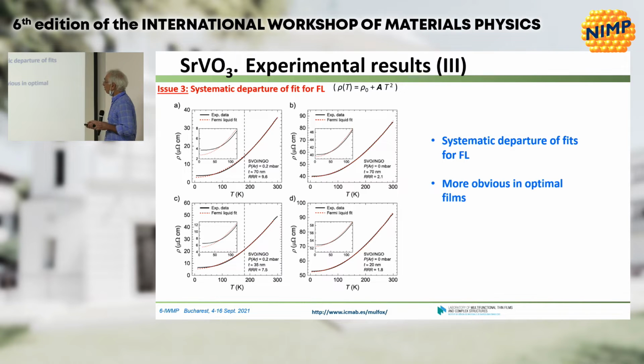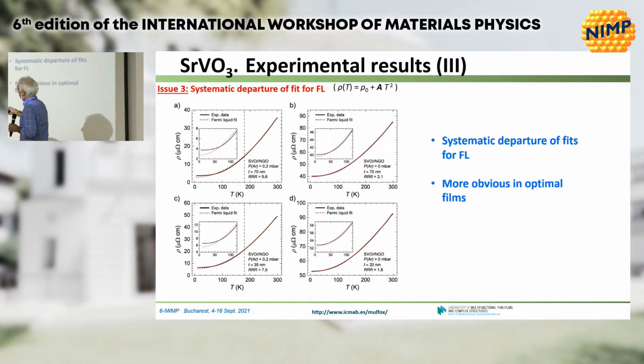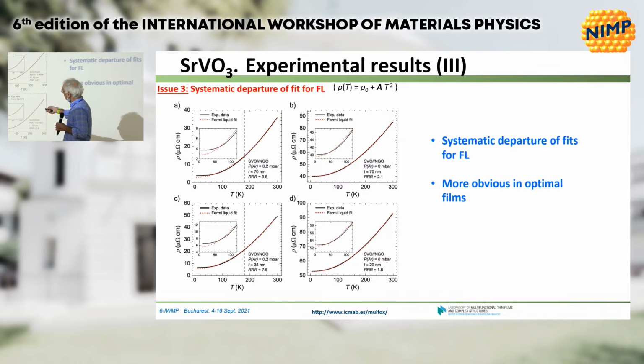As I already mentioned, the quality of the T-square fit is not good. So really, this plot was not a straight line. And this is better seen here. This is the data, and here is the quality of the T-square fit. Obviously, the fit was not good enough.